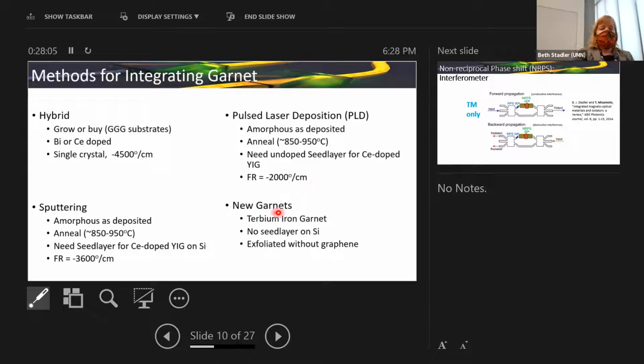So we found this terbium iron garnet that forms garnet without a seed layer. You just put down your resist, put down your terbium iron garnet, strip the resist so you can heat it, and then you get garnet. And you get a pretty good Faraday rotation.